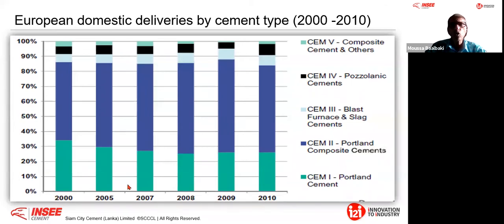What is remaining on the OPC is about 25%, but if you dig into it, it is not indeed 25%. Because very often some ready-mix players in Europe, like in Sri Lanka, get their own slag or their own fly ash and do the blended concrete. Therefore, they use OPC, but the concrete is not OPC concrete.